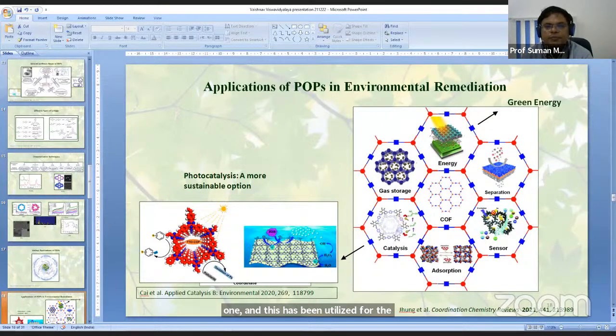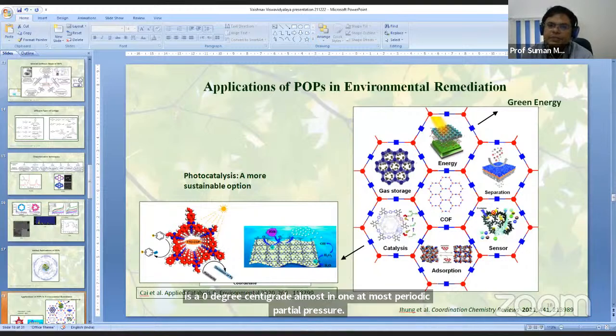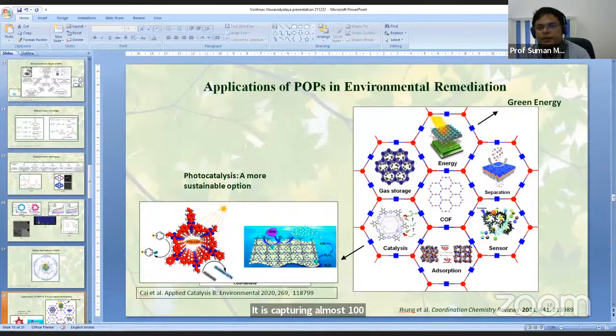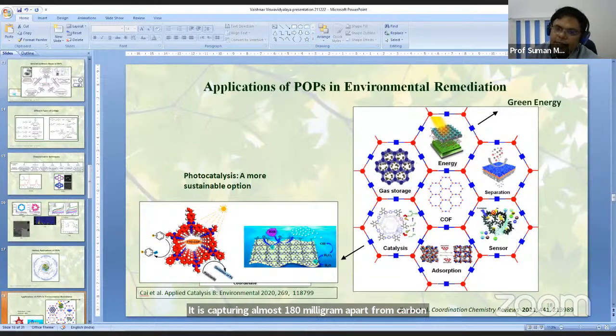The pore size is 0.94 nanometer. And as the pore size becomes smaller and smaller, it becomes easier to capture the gas. They have found that they can capture carbon dioxide gas at 273 K, that is 0 degree centigrade, at almost 1 atmosphere partial pressure. It is capturing almost 180 milligram per gram of carbon dioxide, which is quite high. And at room temperature, it is about 80 milligram per gram. So it can capture carbon dioxide.